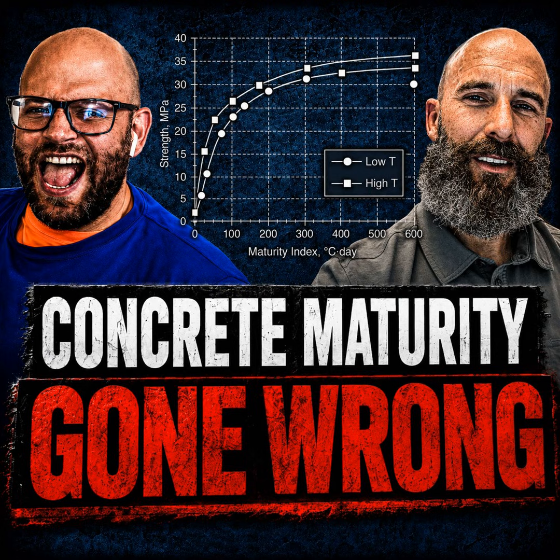And that's why the oil well cement guys use them, because they're going underground where there's a lot higher pressures as well as a lot higher temperatures, especially with the amount that they're pumping and things colliding. So they want the concrete to be liquid longer. Because if we gave them a type 3 cement, it would harden in the line because the temperature is hotter, so it's going to set up faster. That's the thing with concrete and cementitious materials. Temperature begets temperature. Hydration kicks off hydration.